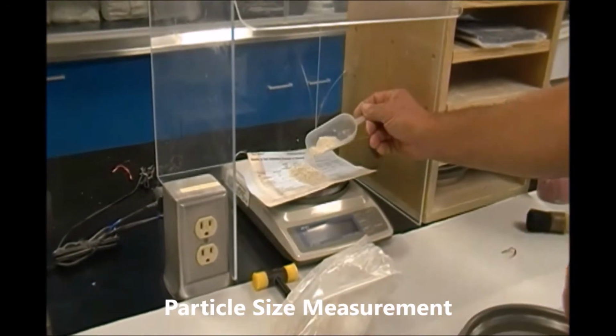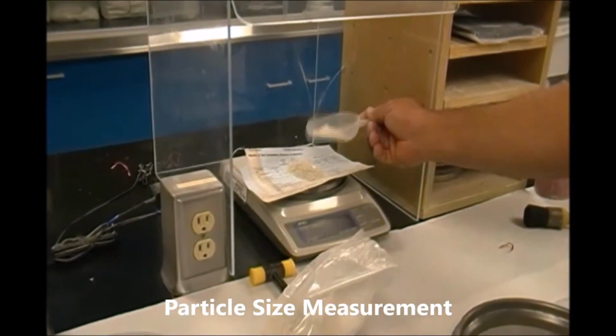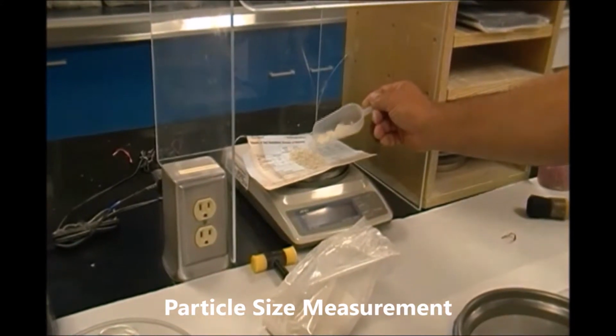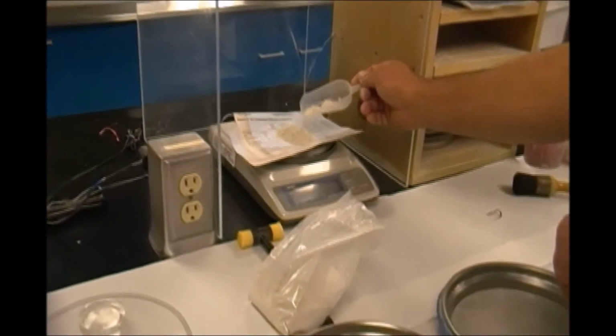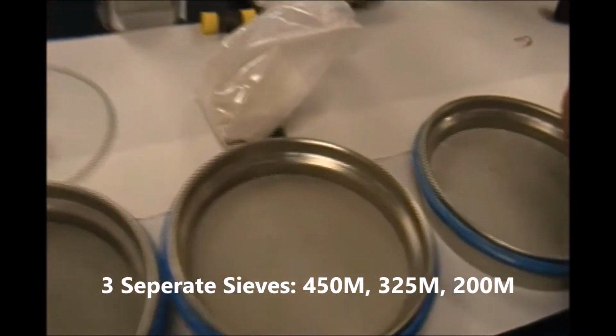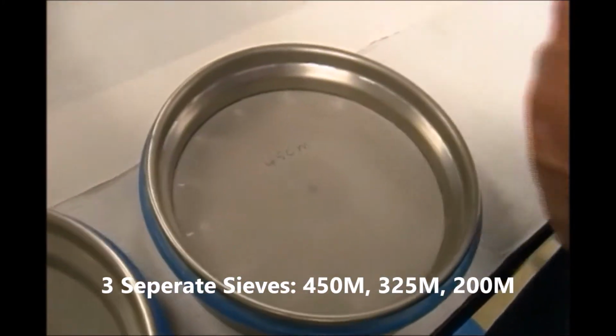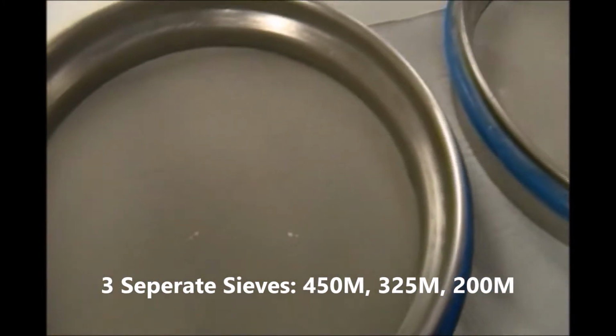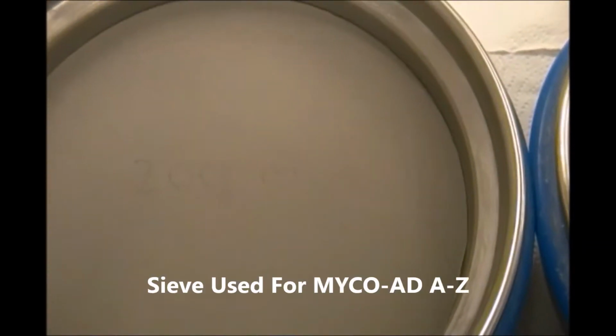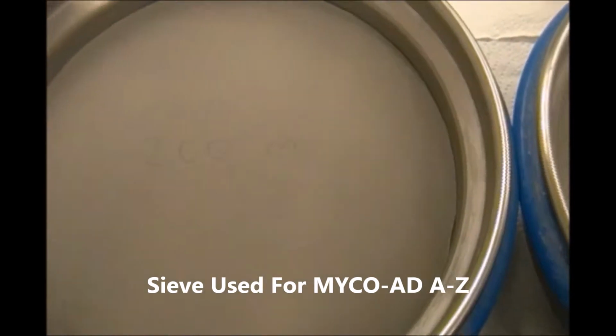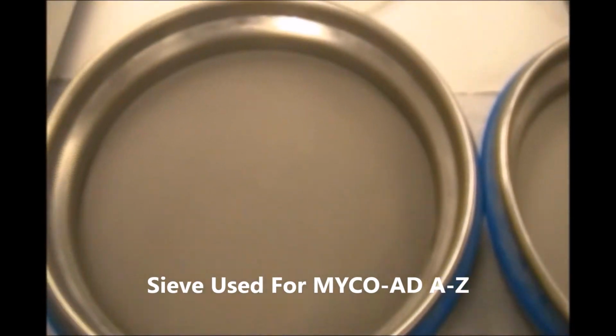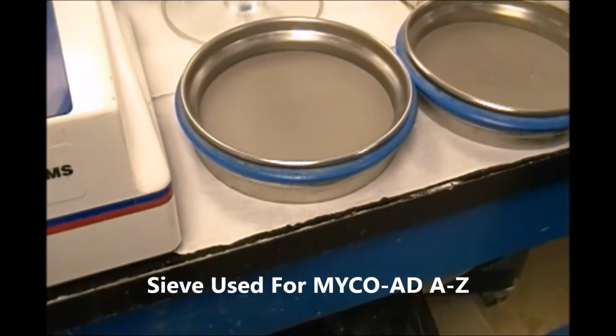In this area of the laboratory is where we measure particle size. What we will do is measure out 10 grams of product. The product will then be put into one of these sieves, which is used for a sieve analysis test. Each sieve is a different size. You'll notice here that we have a 450 mesh screen, 325 mesh screen, and a 200 mesh screen. The 325 mesh screen is used for MycoAd, and the 200 mesh screen is used for MycoAd AZ. In this trial, we'll be using the 200 mesh screen for MycoAd AZ.